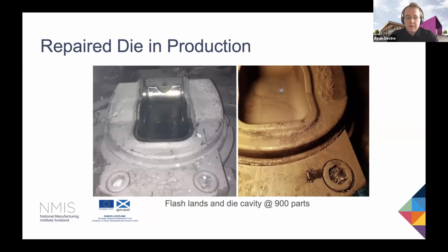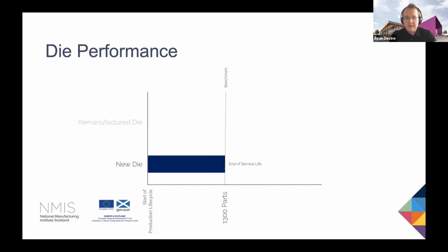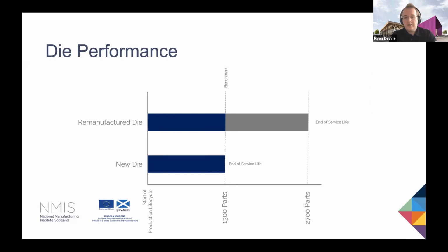At this point in time, the dies were showing really very little wear on the MetcoClad 21 areas, and the performance on them was going really well. It was really high performing at that point. So this was really good for us to see, quite far into what would be a production run, that the dies are still performing really well. So just for reference, a new die would normally produce the 1300 parts. Our die went into service as normal, ran its 1300 parts, but then we were able to get an additional 1400 parts out of that die for a total of 2700.